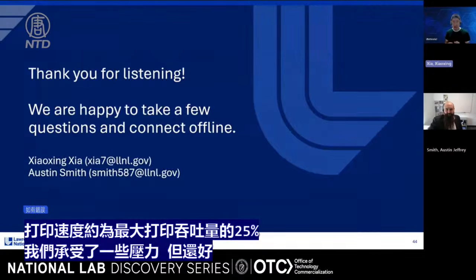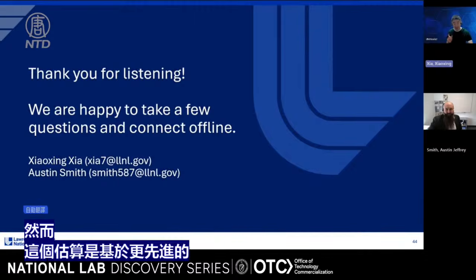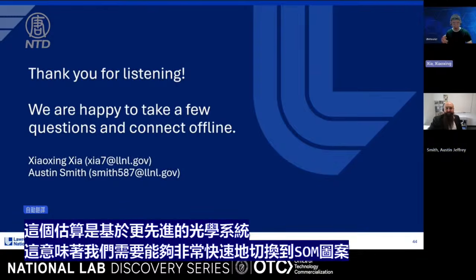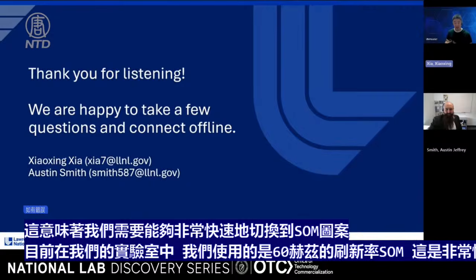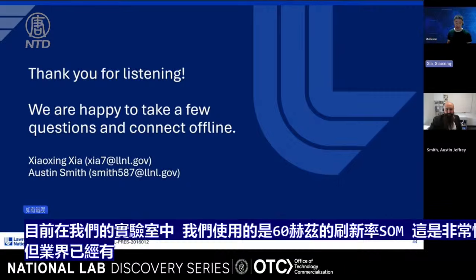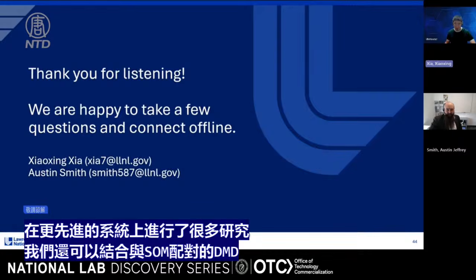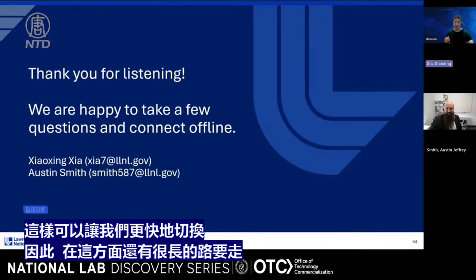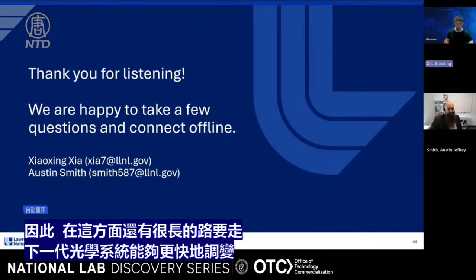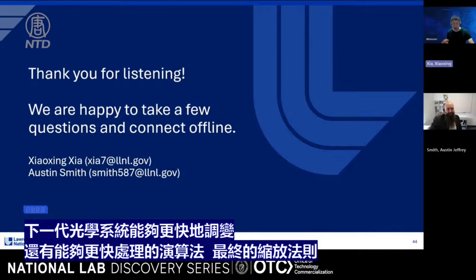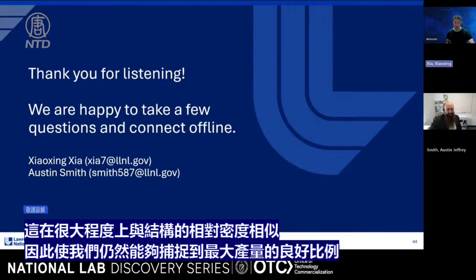However, this estimation is based on a more advanced optical system, meaning that we need to be able to switch the SLM pattern very quickly. Currently in our lab, we use a 60 Hertz refresh rate SLM, which is very slow, but industry has been working on a lot of more advanced systems. We can also combine a DMD that is paired with SLM, so that enables us to do the switching faster. So there's still a long way in terms of next generation optical systems that can be modulated faster, and also algorithms that can process faster. But in the end, the scaling law is largely similar to the relative density of the structure. So that enables us to still capture a good fraction of the maximum throughput.